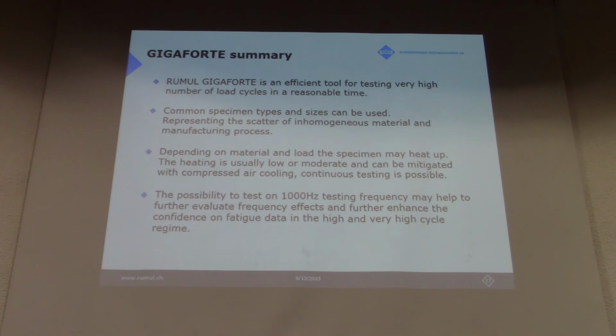So if I summarize, our new testing machine is an interesting tool for doing investigations, especially in the very high cycle fatigue regime. We can use common specimen types, and of course, depending on the material, we also have to look at the heating up of the specimen. But usually compressed air cooling is sufficient, and continuous testing is possible.